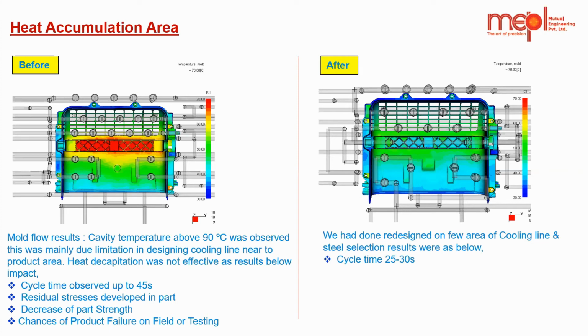After that, we made some changes in the cooling lines and found some results. We reduced the cycle time by 25 to 30 seconds, and we got uniform part cooling and the desired mold temperature which was needed. It also reduces the residual stresses in the part, and we could also reduce the sink marks in the part.